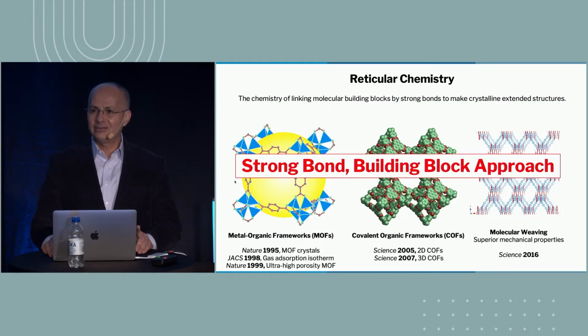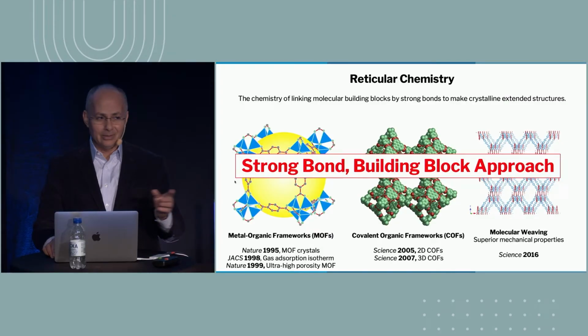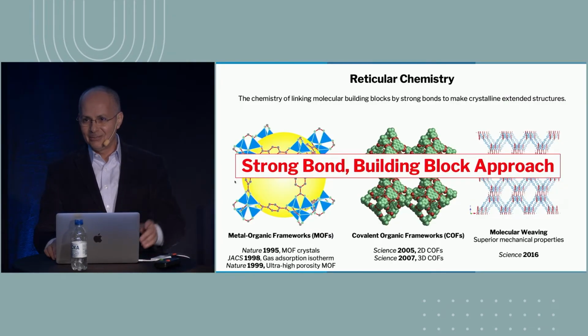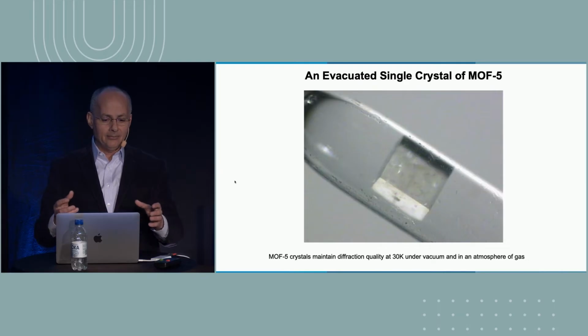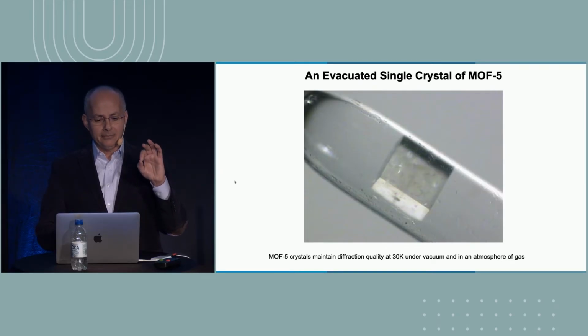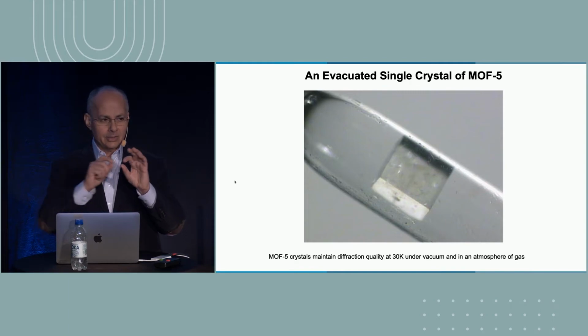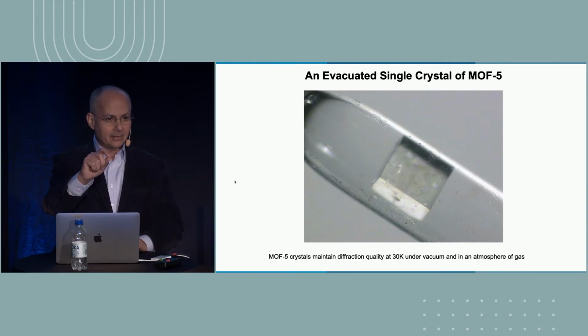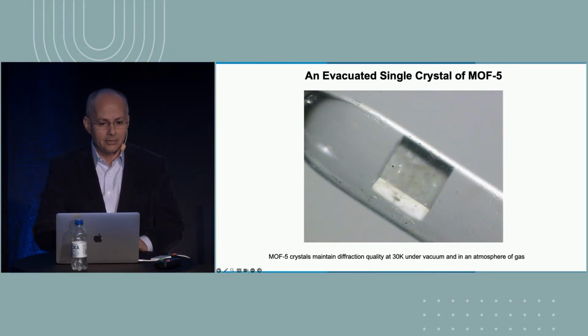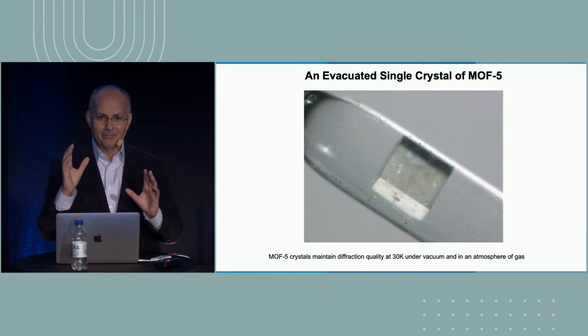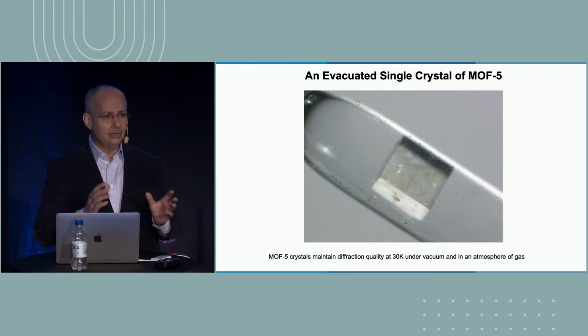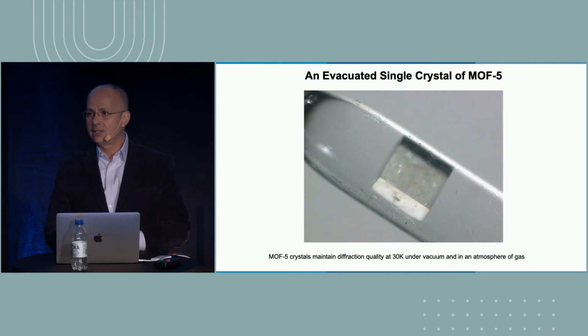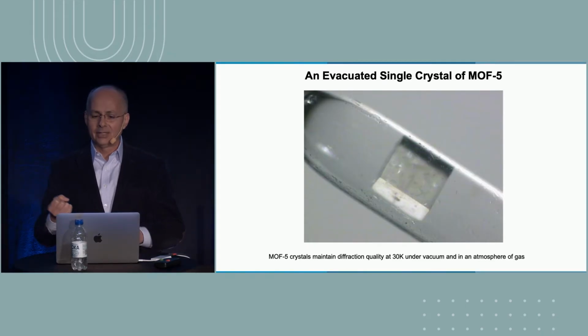So why do they have such a high surface area? Okay, the need to know. Several of the previous great speakers mentioned that, the need to know. And now you take a crystal of this MOF 5, the one with the yellow ball, and you stick it in a capillary and you put it on an X-ray diffractometer. Okay, this crystal has been completely evacuated from all the stuffing that is in the pores, and now you're just looking at the framework. Okay, it didn't break apart. Usually crystals will lose their monocrystallinity when you take away the solvent that is contained within them, but here it didn't.